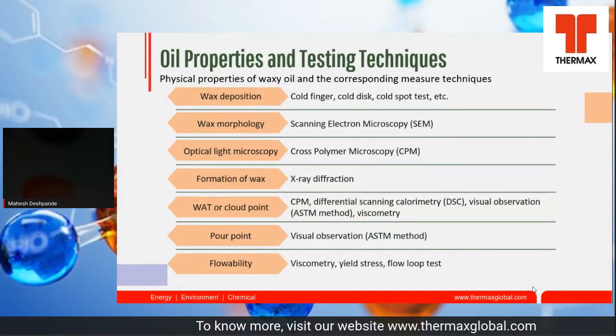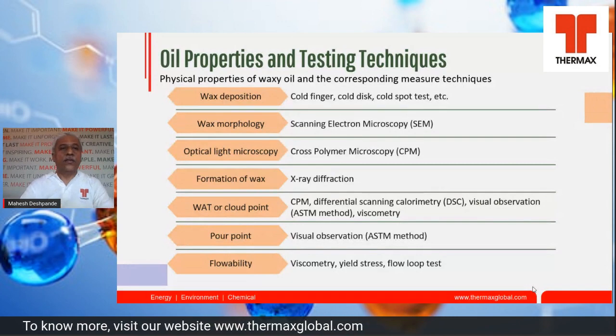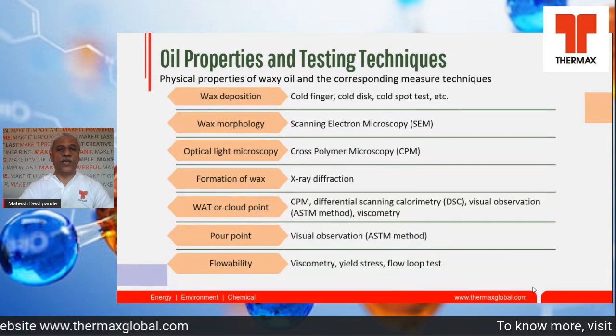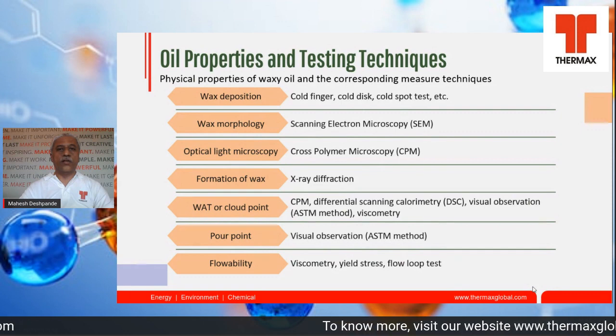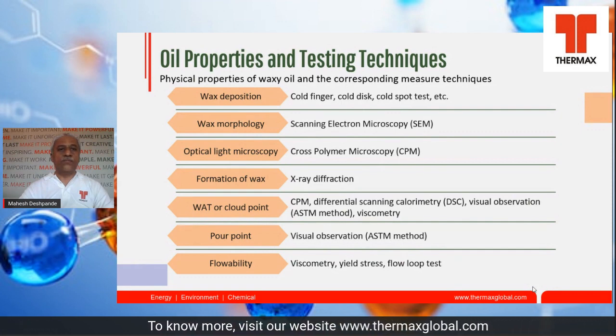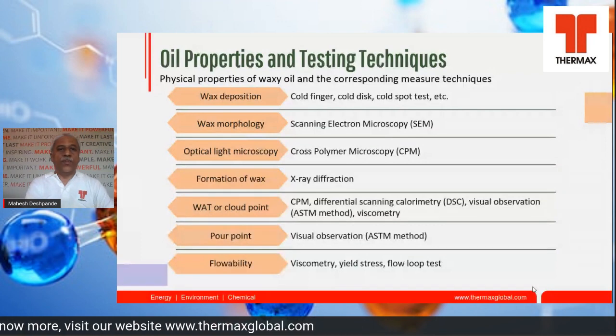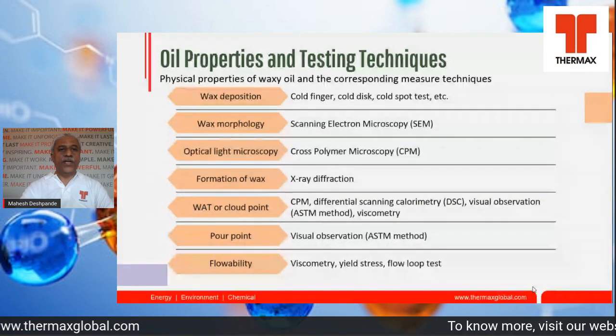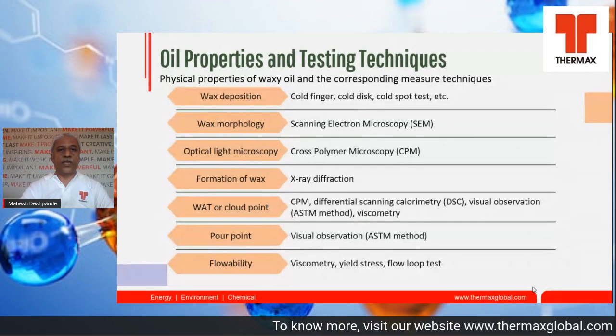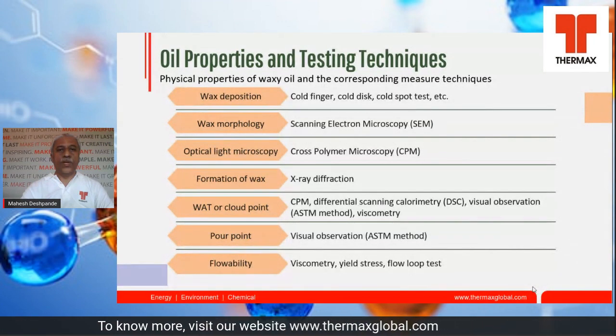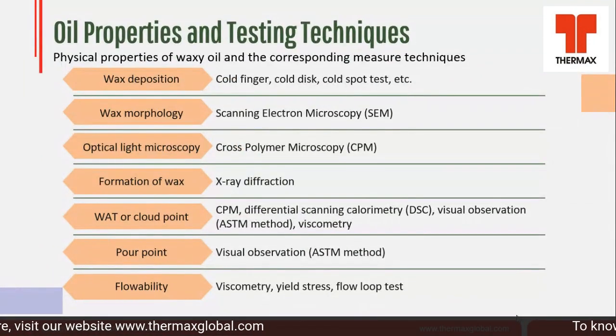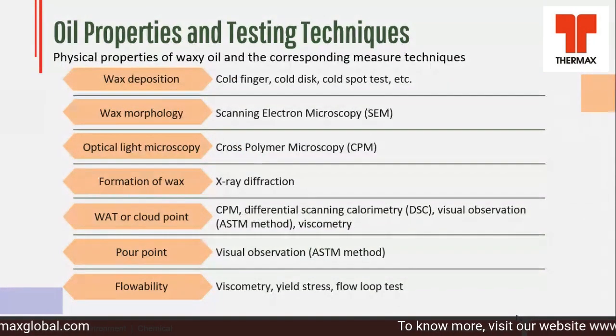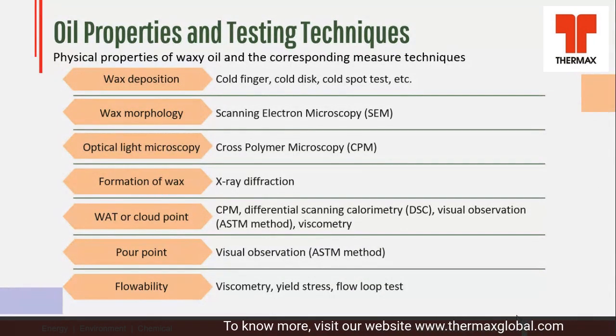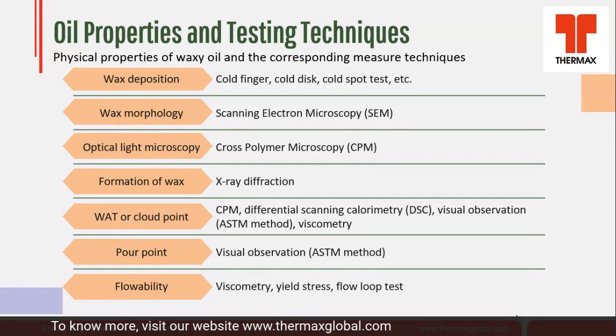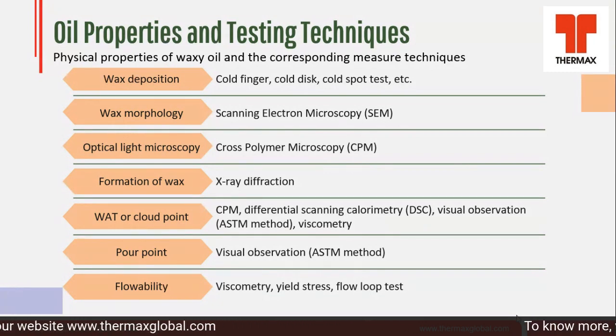Now we will see the properties of the oils and their testing techniques. First, we can see wax deposition, which can be tested by cold finger test or cold disk or cold spot test. Then wax morphology can be tested by scanning electron microscope. Then optical light microscopy can be done by cross-polarized microscopy. Then wax formation can be tested by X-ray diffraction. Then wax appearance temperature and cloud point can be checked visually, or they can be tested by differential scanning calorimeter.